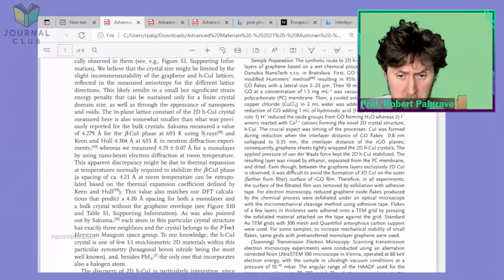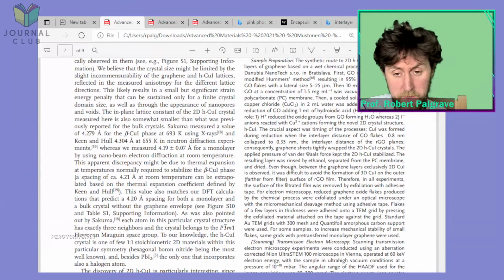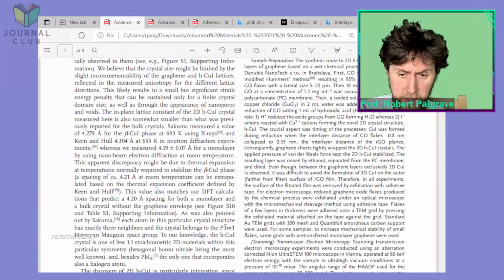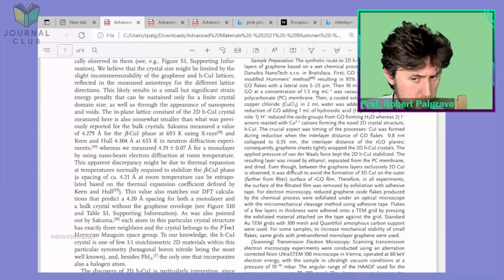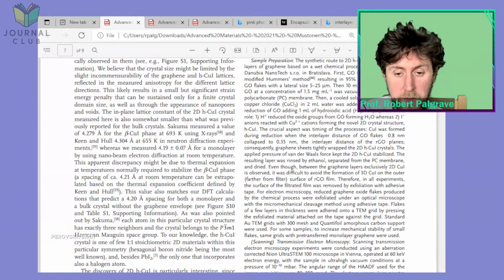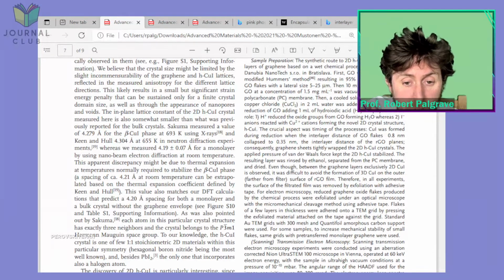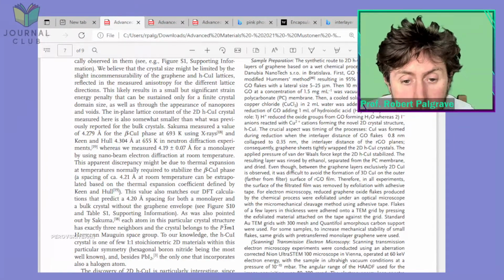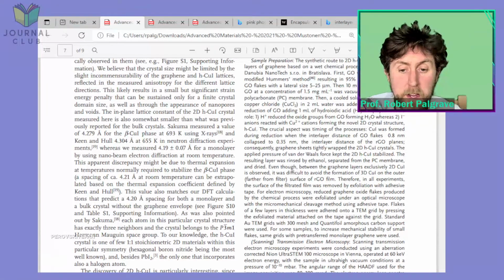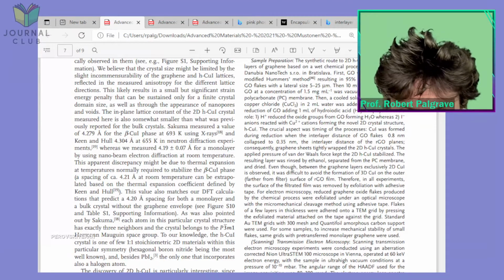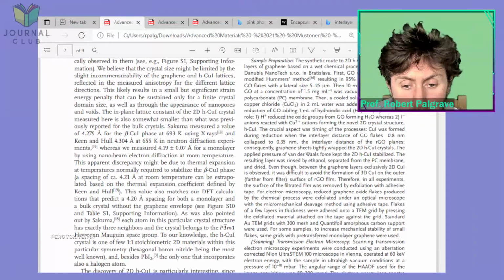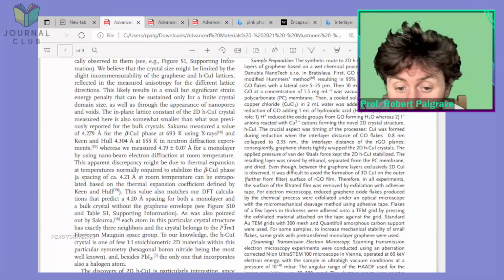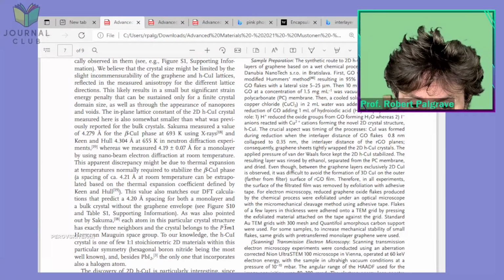For electron microscopy, reduced graphene oxide flakes produced by the chemical process were exfoliated under an optical microscope with micromechanical cleavage method using adhesive tape. Okay, yeah, that's kind of what they said. They did it in a microscope. Very, very fiddly, I imagine, to do that, but I think these guys have probably got a lot of practice. Flakes of a few layers in thickness were adhered onto a TEM grid by pressing the exfoliating material attached on the tape against the grid. Standard gold TEM grid with 300 mesh and Quantifoil amorphous carbon support were used. For some samples, to increase the mechanical stability of small flakes, same grids with pre-transfer monolayer graphene were used.